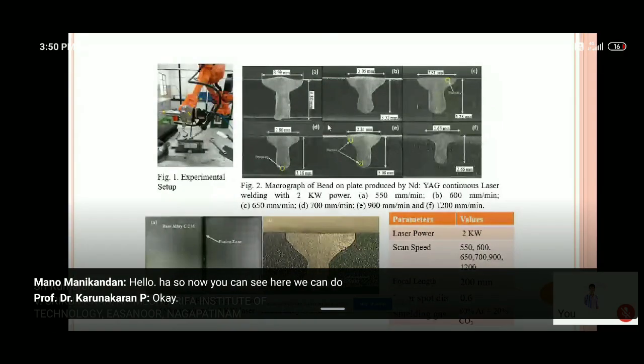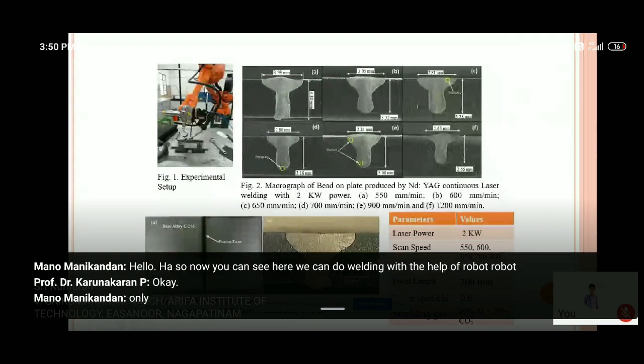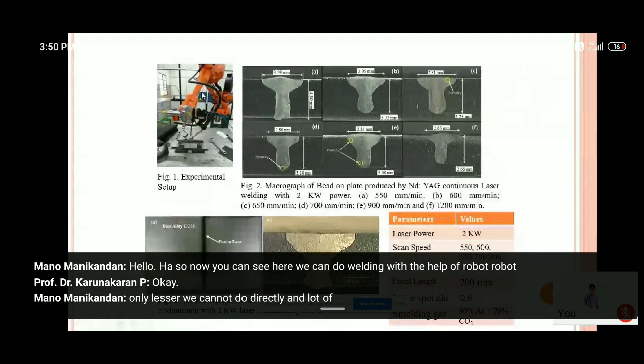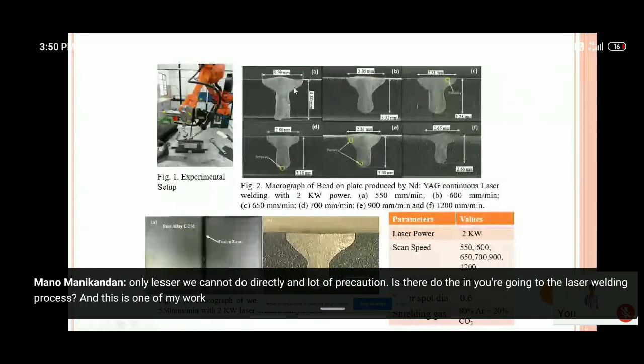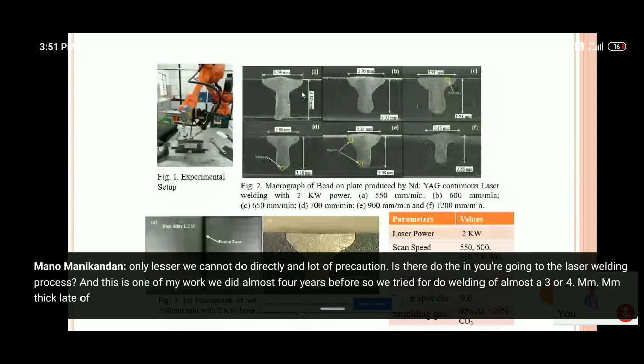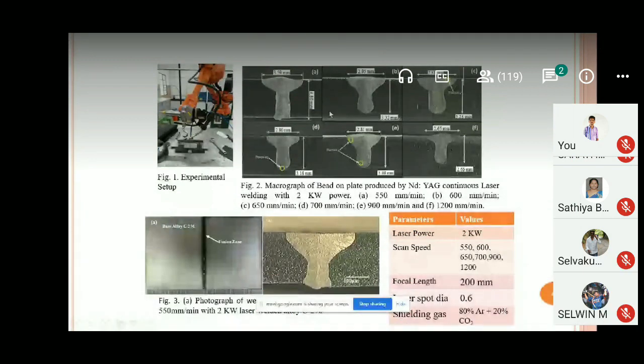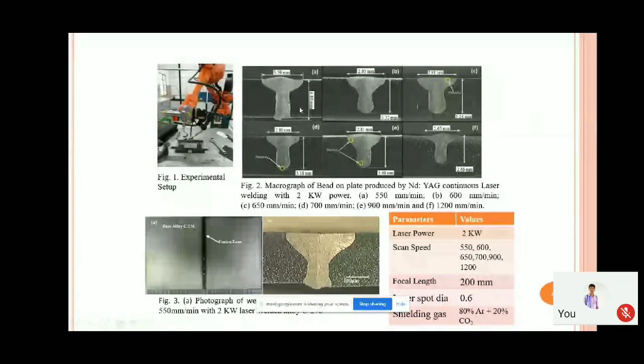We can do welding with the help of a robot only. Laser we cannot do directly, and a lot of precaution is needed when you are doing the laser welding process. This is one of my works we did almost 4 years ago. We tried welding a 3 or 4 mm thick plate of Hastelloy C276. We did a lot of trials first to optimize the process parameters, and finally we achieved the entire depth of 4.8 mm. And we compared the laser welding study with TIG welding of the same material.